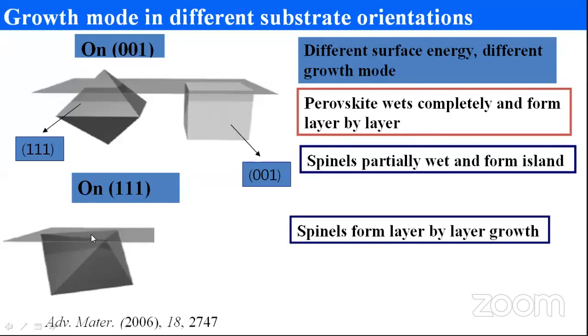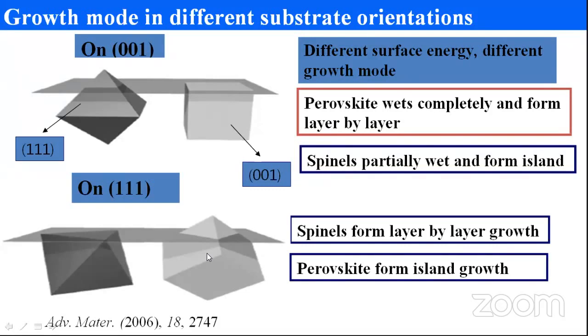So the spinel will grow layer by layer, and then your perovskite will wet partially, and will grow as a column. Just by changing your substrate orientation, you can change whether you need a cobalt ferrite or spinel column, or a perovskite column; whether you need a ferroelectric material as a rod, or a ferromagnetic material as a rod.